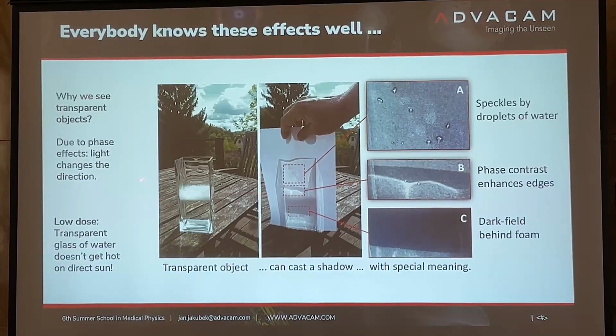So, I have highlighted a few. Behind the foam, we see a darker region, which is dark field. That means that the light was scattered out, so it doesn't continue straight. It goes in all directions. Close to the edges, we see this kind of enhancement because the light would be directed to another place, and you would have more light coming here. So the light which would normally fall here, comes here. So that's the phase contrast.